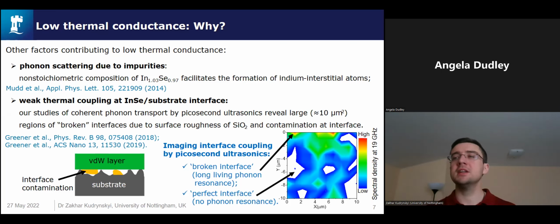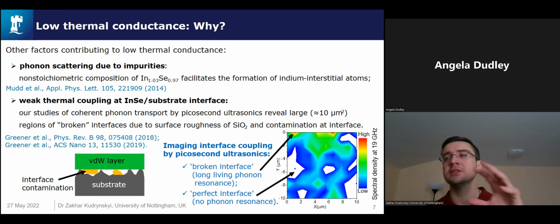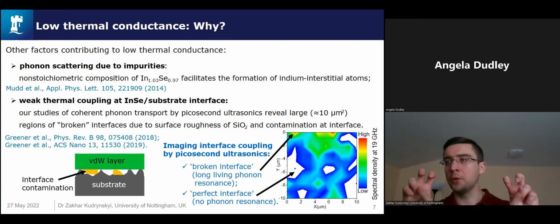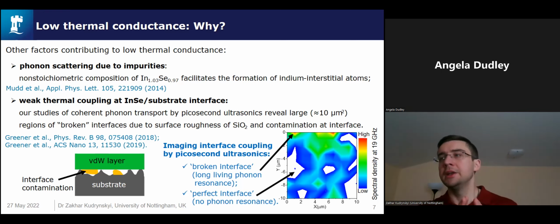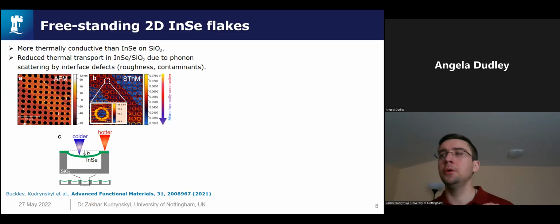Our previous studies of coherent phonon transport by picosecond ultrasonics revealed large regions of up to 10 square microns of so-called broken interfaces, where the indium selenide layers are weakly coupled to the supporting substrate due to surface roughness of silicon dioxide and contamination at the indium selenide silicon dioxide interface. So a thermal coupling between indium selenide and silicon dioxide is reduced, causing an interfacial thermal resistance and suppressed heat dissipation from the flake. To assess further the role of the substrate, we have investigated freestanding indium selenide flakes, as well as flakes supported by different substrates.